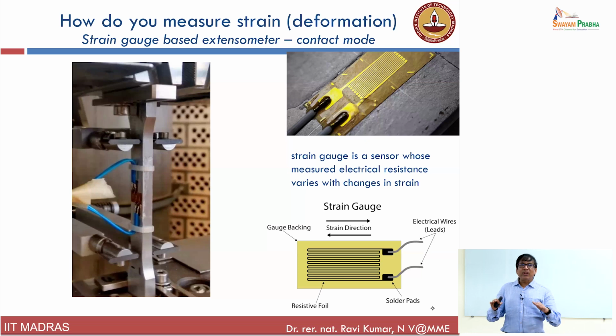Now, these are some very basic things. A technician should do that, but nevertheless, we should be aware of it. And the biggest challenge is to measure strain, because when you do a typical tensile test, you need to measure strain. And for metallic materials, again, it's not a problem. But ceramic samples, it's a problem. Why? Because the strain in a ceramic sample is very low. In fact, 0.5% is a failure strain of many ceramic materials. That means you are dealing with extremely small strains. And when you have very small strain, your ability to measure strain should be very, very accurate. Otherwise, you will not be able to get correct data.